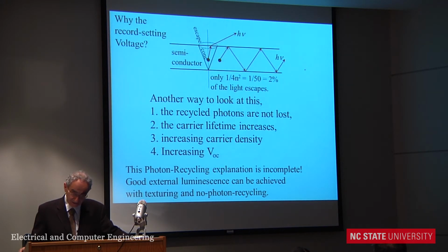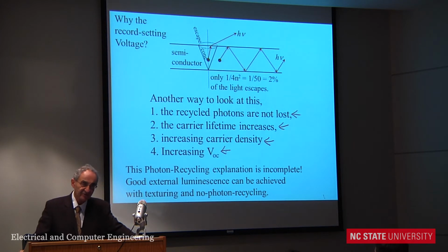Well, here's one possible explanation: the recycled photons are not lost. They recreate the electron hole pairs. The effective electron hole lifetime increases. If they hang around more, you can build up higher density. I already said the log of density is voltage. So this is one possible explanation to think about this. And this is one that some people like. But this is a very incomplete explanation. For example, you don't have to recycle the photons. You can just texture the film. You'll still get the voltage increase.